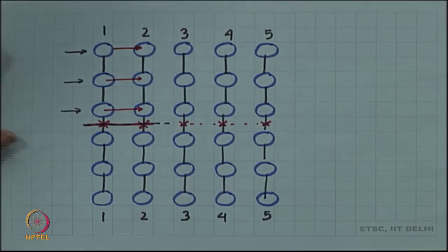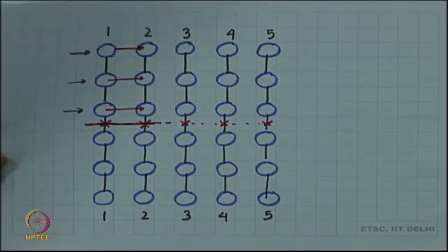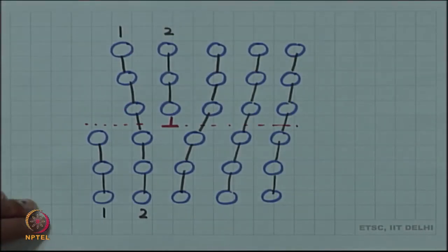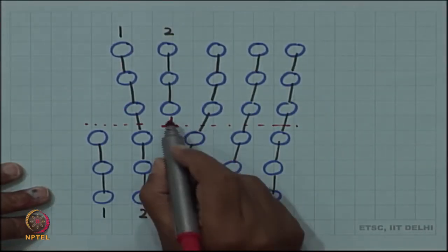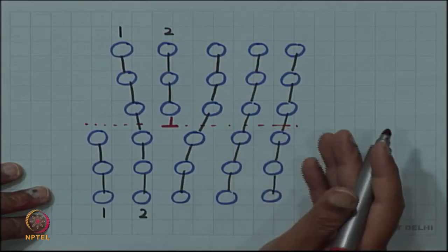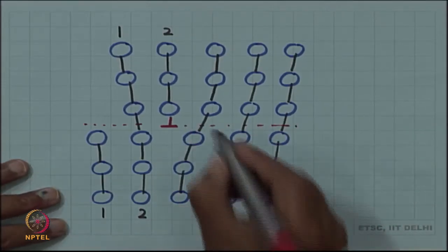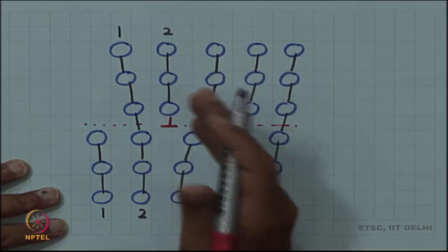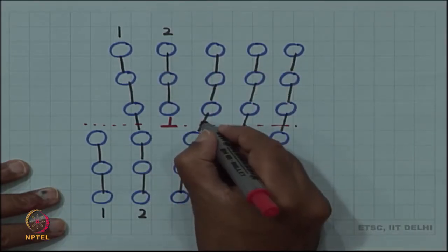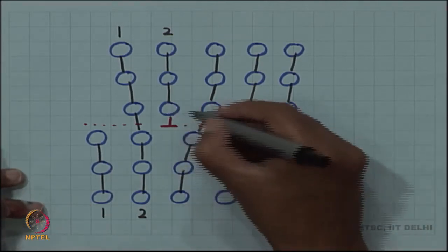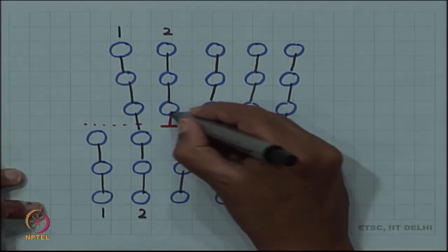So, that will require a higher energy and correspondingly a higher stress to achieve it, whereas in this case, for each unit step from now onwards I have to cut only one set of bonds. So, to create further deformation, I will just cut this bond such that this bond now rejoins here.